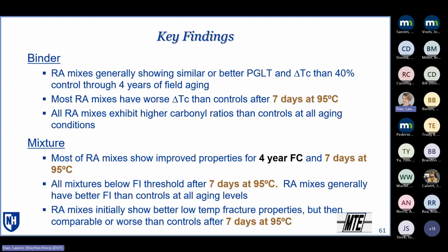From the mixture testing, most of those RA mixes still show better performance for the 4-year field cores and for the 7-day aging. For the intermediate cracking thresholds, once we get to those longer term aging, everything's basically hitting the bottom. Generally, those RA mixes have better values than the controls, but again, once you're below the threshold, nothing's really any good. And then the RA mixes initially show better low temperature properties, but that's diminishing with the increased aging.